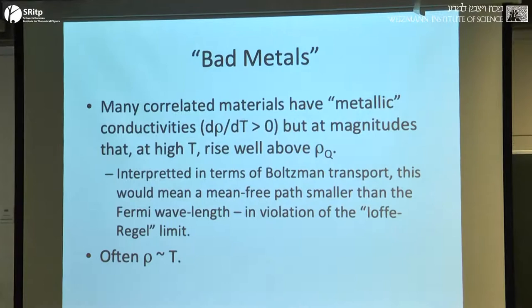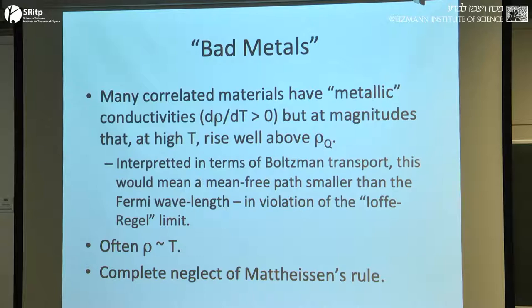And in fact, often the resistance is seen to be linear in temperature. And by the way, something else that's not always stressed, but one of the other features of Boltzmann transport theory is Matthiessen's rule, which says that whatever is giving rise to the resistivity, when you add some other scattering mechanism, that scattering mechanism tends to increase the resistivity. So whatever is causing the resistivity, if I heat the system up, say, past some optical phonon frequency, I would expect to see some increase in the resistivity as scattering by some new set of optical phonons onsets. And one thing that these bad metals do is they ignore the optical phonons.